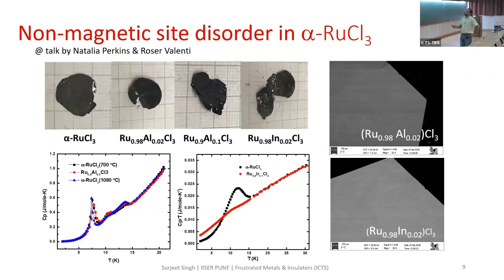And for the underlying motivation, you can look at these presentations. The bad news is that it's very difficult to dope RuCl3. We tried doping it with aluminum, we tried doping it with indium. And the reason why we took aluminum and indium is because both AlCl3 and InCl3, indium chloride, also crystallize with the same structure. So they are isostructural to RuCl3, and yet it's very difficult to dope them at the ruthenium site. On the other hand, it's relatively easier to dope iridium, which we have managed to do, and now we are trying some other substitutions.